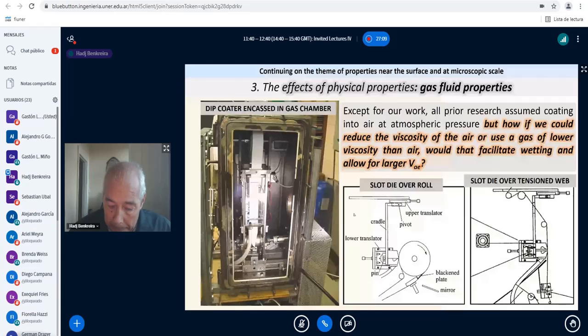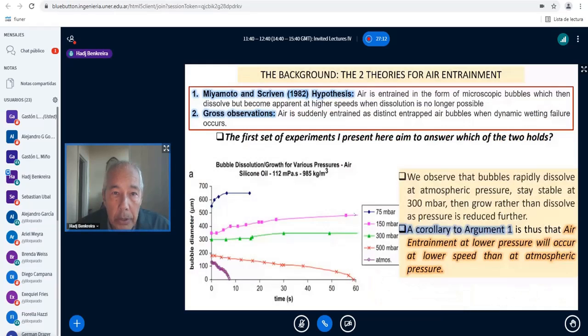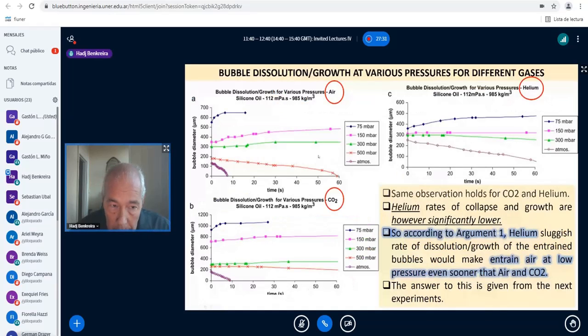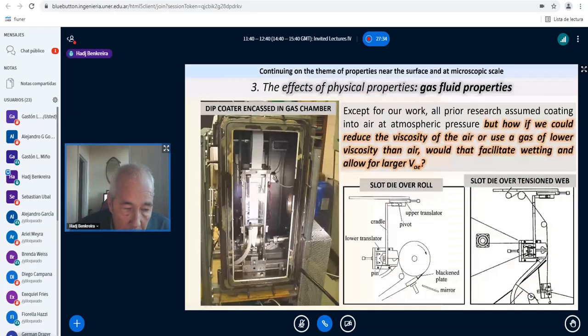And prior to our experiment, there has been no experiment to really check this hypothesis number one. So what we did, the first experiment, we looked at the air bubbles that were being entrapped into the liquid as you decrease the pressure. And as you see in here, we did experiment at atmospheric pressure, and then we reduce it to 500 millibar, 300 millibar, 150 millibar, 75 millibar, and this is using silicone and in air.